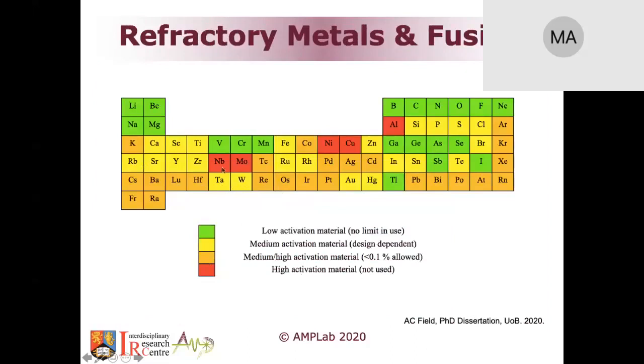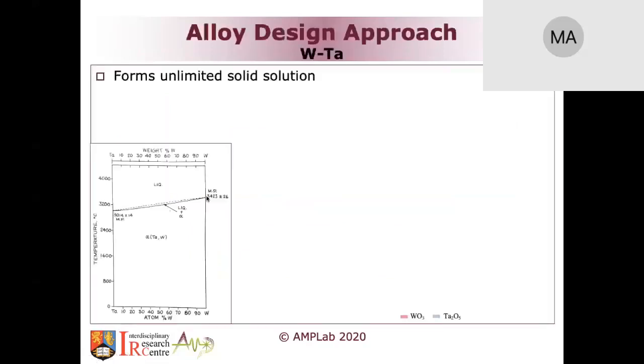Elements like niobium, moly, nickel, copper, and aluminum, they never want inside a nuclear fusion environment. Whereas yttrium is okay, zirconium is okay, tantalum, of course, is okay, tungsten is okay. Rhenium is not among the favorites, and it's also not favored from a cost point of view. So we said, okay, we're going to work on a tungsten tantalum alloy. Now you look into the phase diagram of tungsten tantalum, and it's very nice. The two elements love each other. They form a solid solution between them, which is really nice. The material transforms from a single phase, an unlimited solid solution.